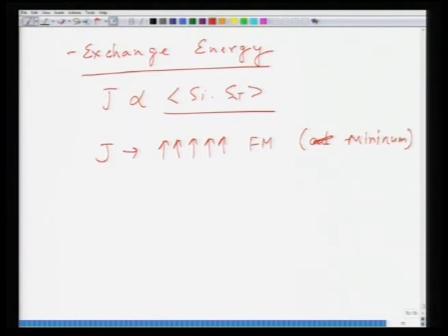for a parallel configuration, but for anti-ferromagnetic materials, as we will see later, this J happens to adopt a minimum in the anti-parallel configuration. So, this J integral, which represents the exchange energy, plays an important role in the alignment of these spins in one direction. You can still call it an internal field, but it's not an internal field as such. It's this exchange energy, which is because of alignment of spins, because of the product of these spin magnetic moments,